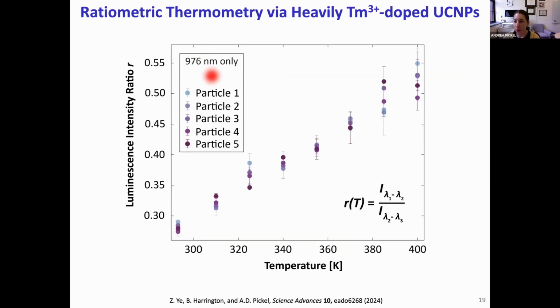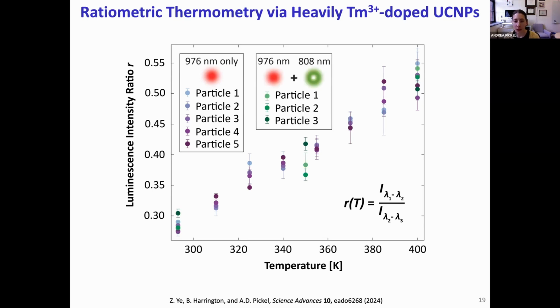These measurements were performed using only our excitation laser, and we'd expect to get similar results if we also apply our donut-shaped depletion beam. To verify that, we did the very challenging experiment of temperature-dependent single UCNP STED spectroscopy. And adding in those results, we confirm that, as expected, they fall in line perfectly with our other data.